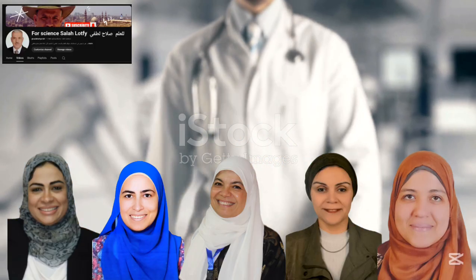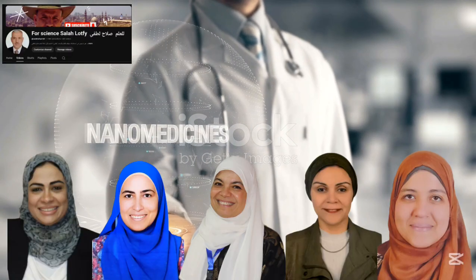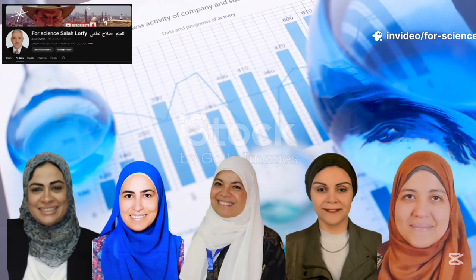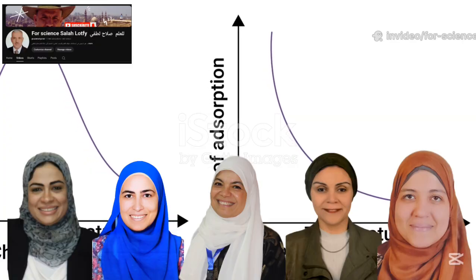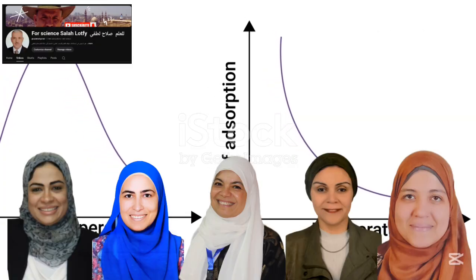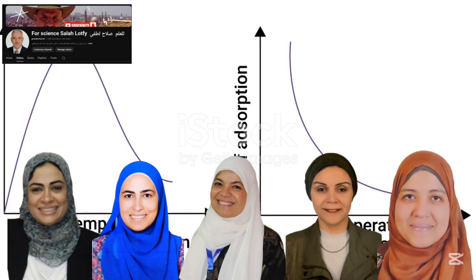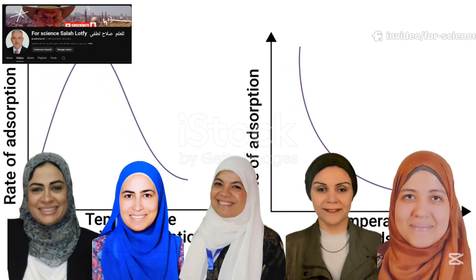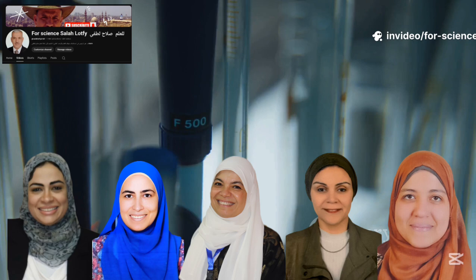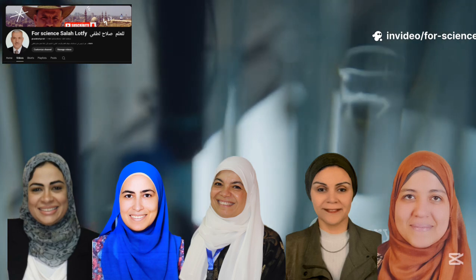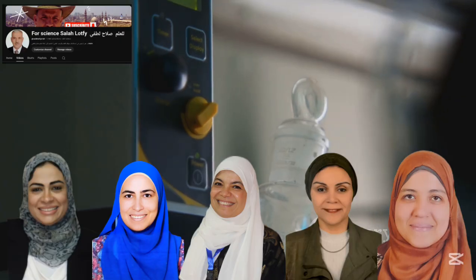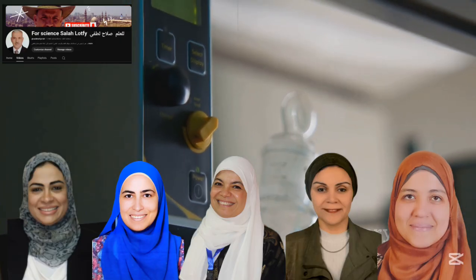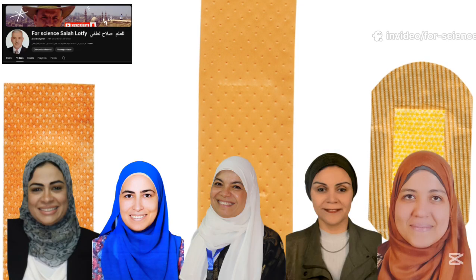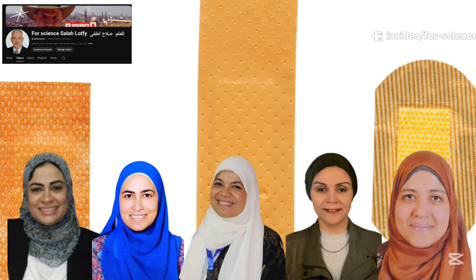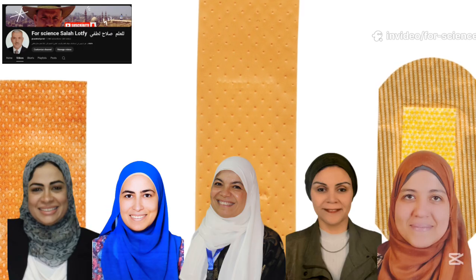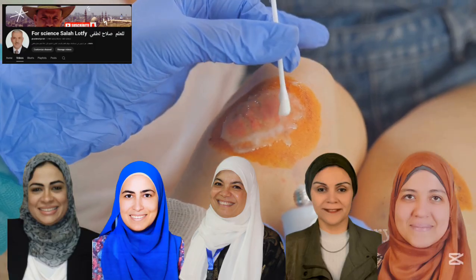The ability to absorb wound exudates was tested using pseudo-extracellular fluid. Plain hydrogels absorbed up to 709%, with lavender oil, absorbance decreased: 618% for 1% LVO, 486% for 5% LVO, and 419% for 10% LVO. Water vapor transmission rate, WVTR, is another critical property. The plain hydrogel recorded 394 g/m²/h, within the optimal healing range. Ag-ZnO reduced it slightly, while 10% lavender oil lowered it further to 271 g/m²/h. This ensures moisture balance, not too dry, not too wet.